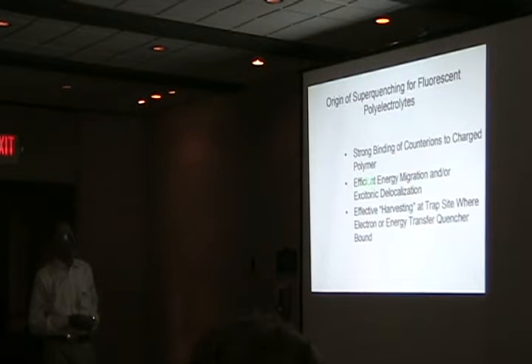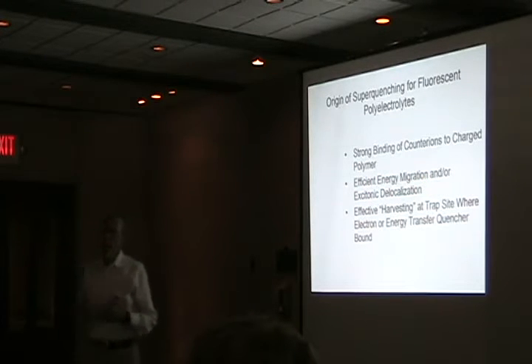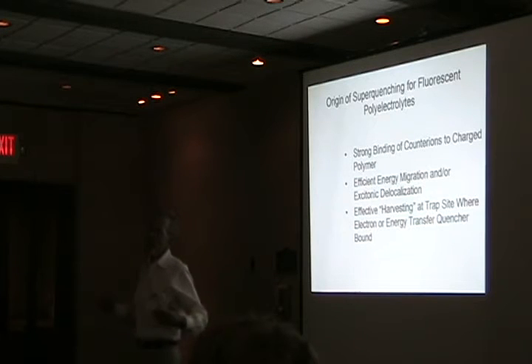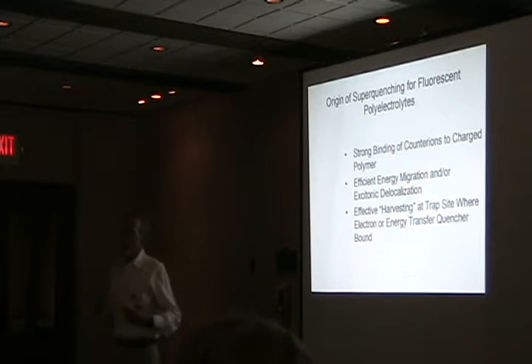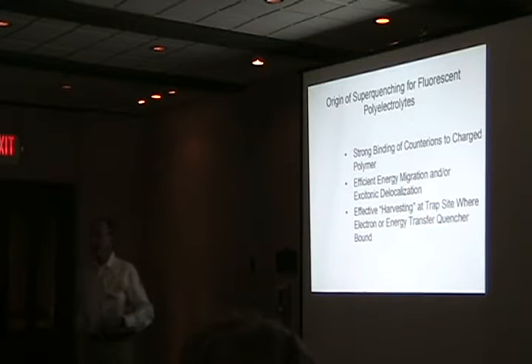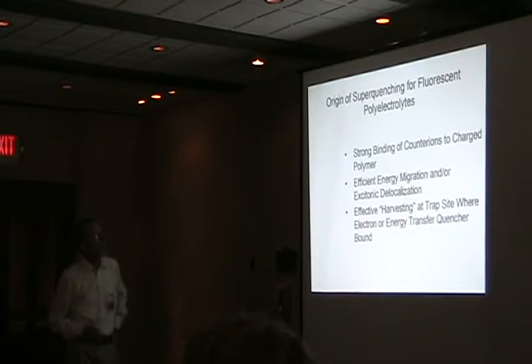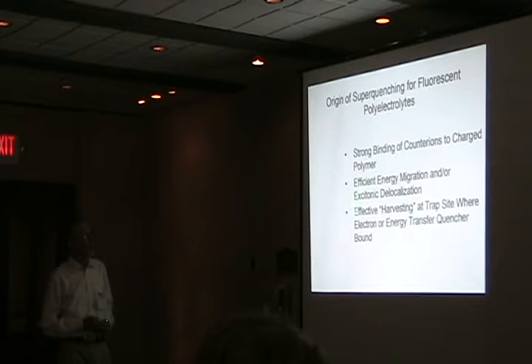You can affect this quite a bit by putting something in the aqueous solution with the polymer. For example, if you add an oppositely charged surfactant at very, very small amounts of surfactant, you find the fluorescence efficiency goes way up. But of course, when it's extended like this in a polymer brush, then we find that there's more difficulty in quenching. The quenching rate constant goes down.